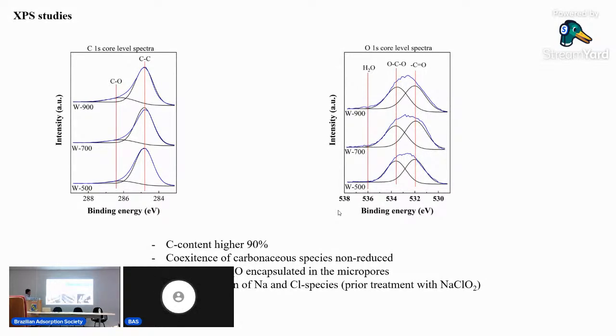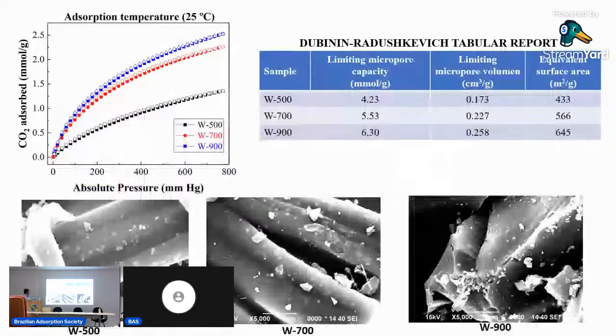And here we have the absorption capacity depending on the calcination temperature, sorry, the pyrolysis temperature, showing a higher absorption capacity with higher temperature. This is the limiting micropore capacity and the equivalent surface area. It's very high.